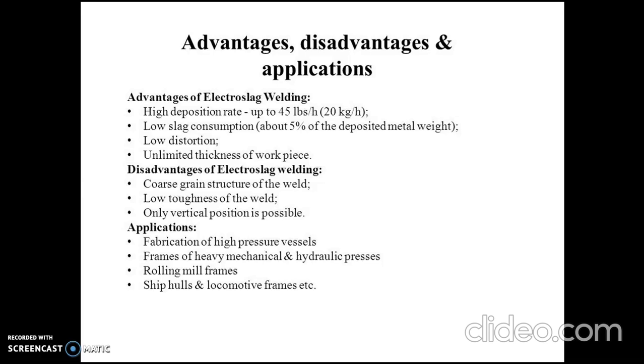It has a low slag consumption, that is a very good thing here. Low distortion, crack formation is lesser, and unlimited thickness of workpiece. Then the disadvantage is the coarse grain structure of the weld is developed, and toughness of the weld is lesser. Means the capacity of energy storing during any mechanical working process is lesser, and only the vertical position is generally possible. That is a limitation of such type of welding process.